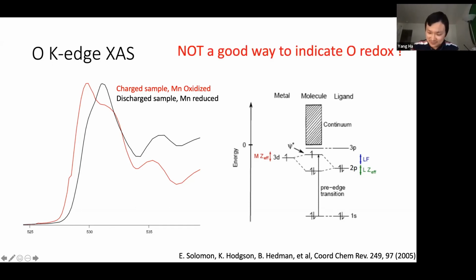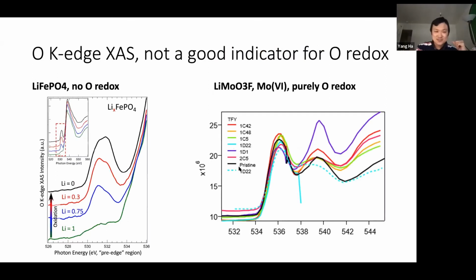So we actually have two examples here from both ends. In this example, it's lithium iron phosphate. So we know when we cycle this material, we're actually cycling the iron between iron 2 to iron 3, and there's no oxygen redox because oxygen is with the phosphate. But here we see a dramatic change.